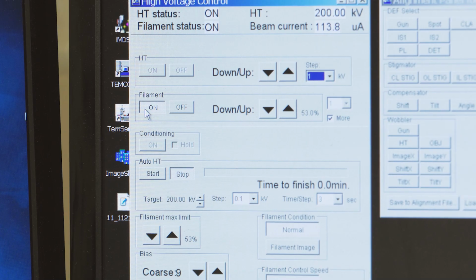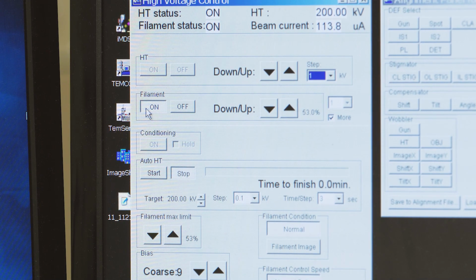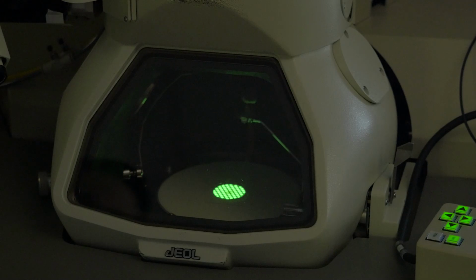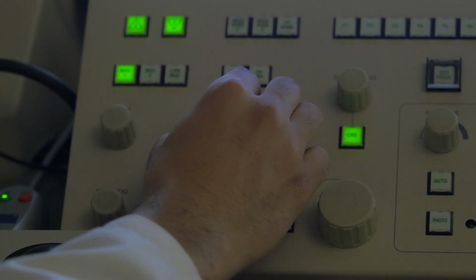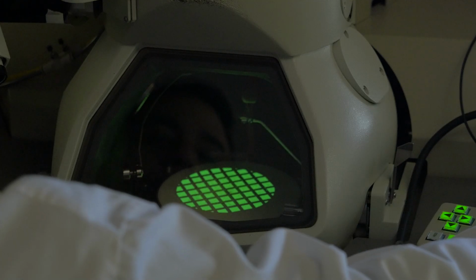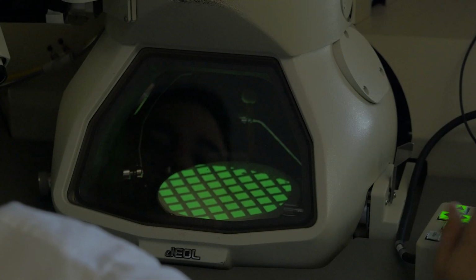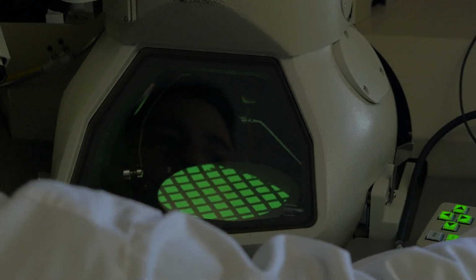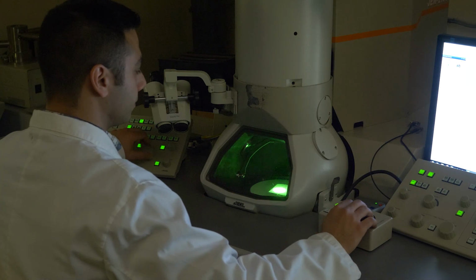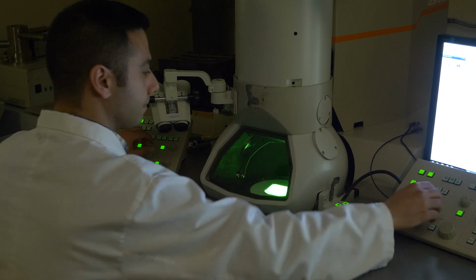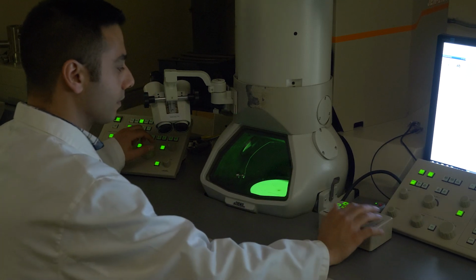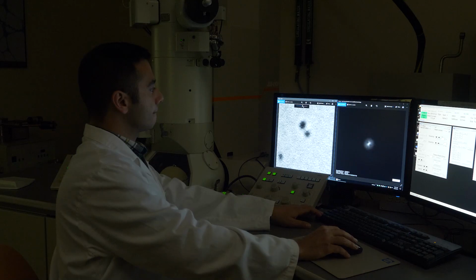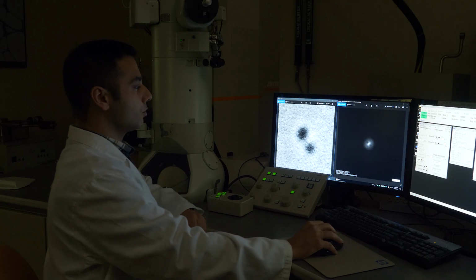Now we are turning on the filament to generate the beam and expose to the sample. It takes a minute to warm up. Then we need to align the beam on our sample, which makes us able to see our particles very clearly. Sometimes this can take a long time. Now you can see how our carbon quantum dots look like under the microscope. These dots are amorphous and round-shaped with a particle size in the range of 2 to 10 nanometer.